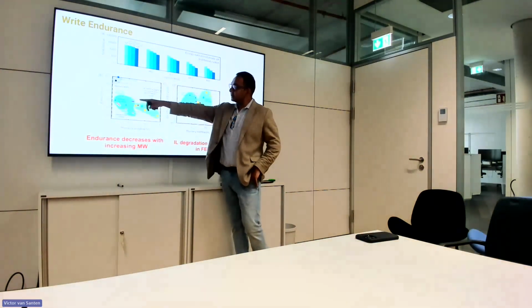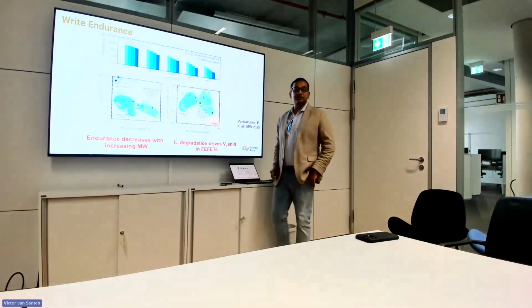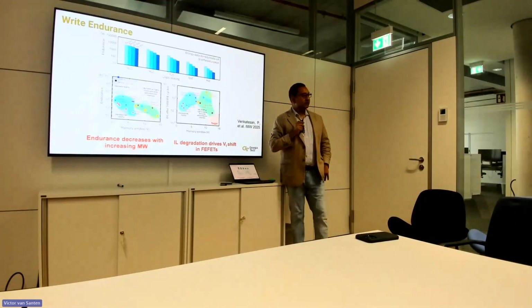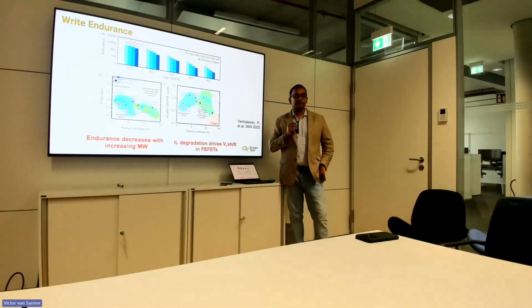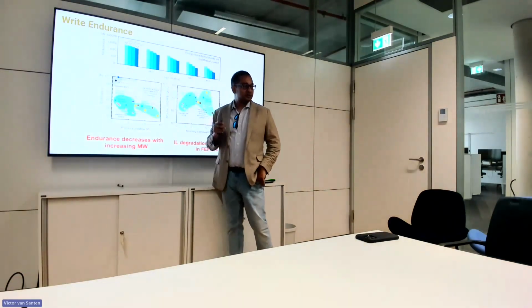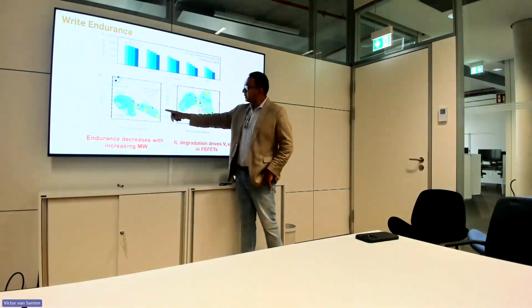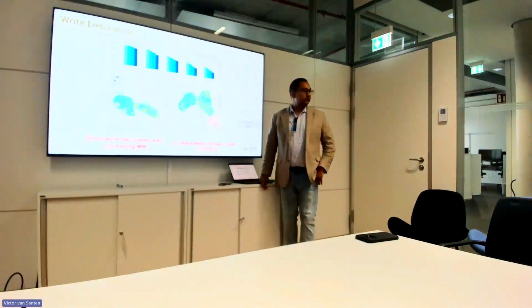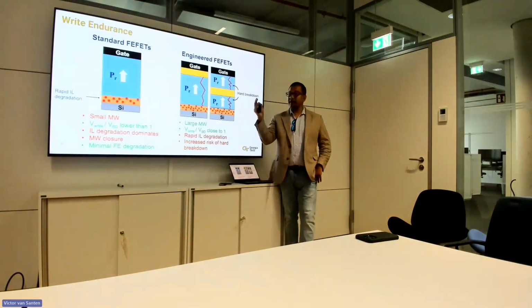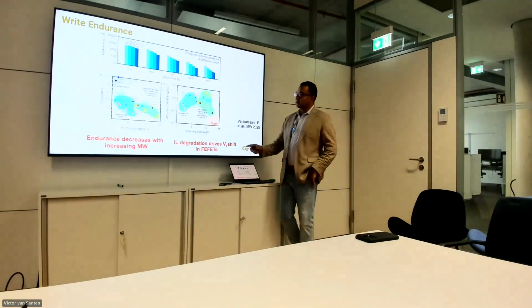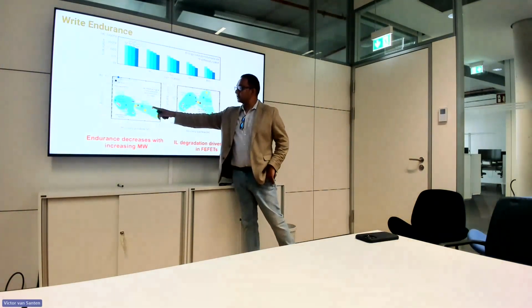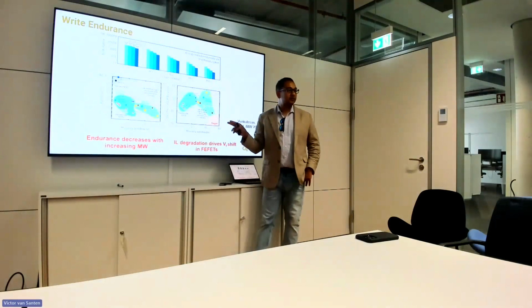Now, if you look at this diagram over here, the y-axis is the write endurance, the x-axis is the memory window. One clear trend you see is that if you are at the lower end of the memory window, you can actually reach 10^11 or 10^10 cycles of write endurance. But on this side, where you have of the order of 10 volts or 15 volts of memory window, we get around 10^4 cycles or 80,000 cycles, or if we stretch, we'll get 10^5 cycles over here. So the bottom line is that as you increase the memory window, the endurance that we get goes down.